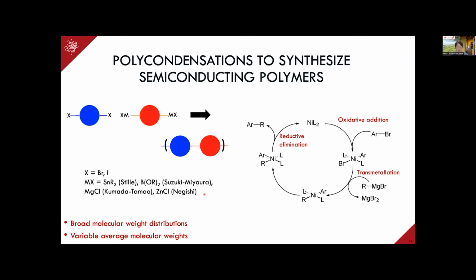But the unfortunate thing about this is while these do give the polymers that you need, because they are basically based on a step growth polymerization, this polymerization results in broad molecular weight distributions. So you have a sample with different molecular weights present. And another issue that we face is that in step growth polymerizations, it's very difficult to control the average molecular weight of your sample. So in order to overcome this,